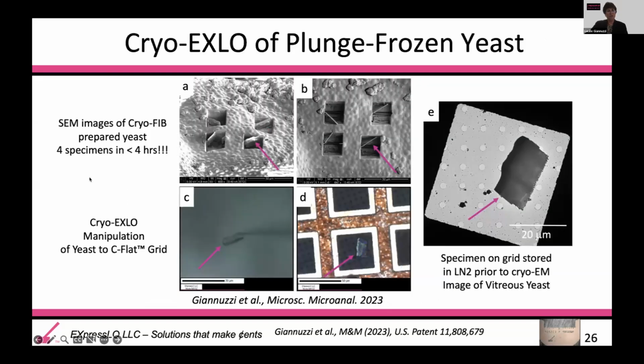We have done this also on plunge frozen yeast. And one of the other advantages of this technique, and some of it I think is our FIB experience, is that we can make 4 specimens, for example, in 4 hours. We can do this pretty quickly. Here's what the specimens look like after they're completely FIB milled free and cut free. They remain touching inside of the trench.